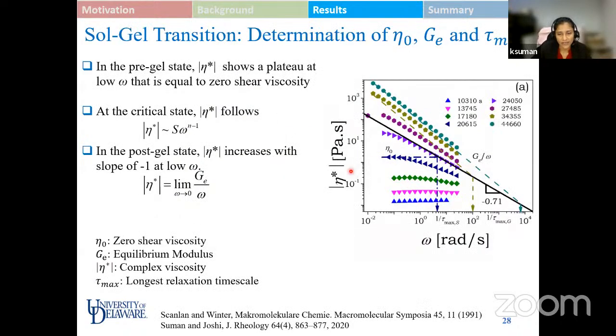So having characterized the gel point time of laponite dispersion, we now plot complex viscosity, which is eta star, as a function of frequency. So this is no new experiment done over here. It's the same experiment which was done at multiple frequencies. It's just plotted in a new fashion. So complex viscosity eta star is given by the rheometer. We collect the data and plot it as a function of frequency right now.